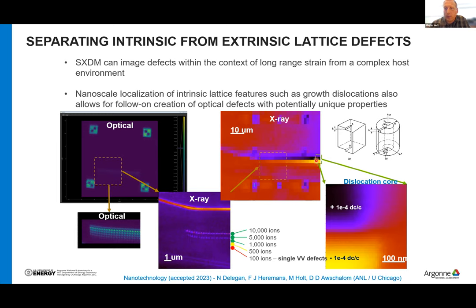And so within the actual crystallographic unit, you can find the performance of these more or less defects that you would like to have in your system in the context of a very complex local environment. And since you can find this dislocation core, you can see this very atomic scale interface of strain variation in real space. And this is very difficult to access through other coherent diffraction methods that can't easily laterally scan, right? And then we can give it back to Sandy and they can start depositing defects that bridge these interfaces and are independently addressable, even though there might only be 20 or 30 nanometers apart.